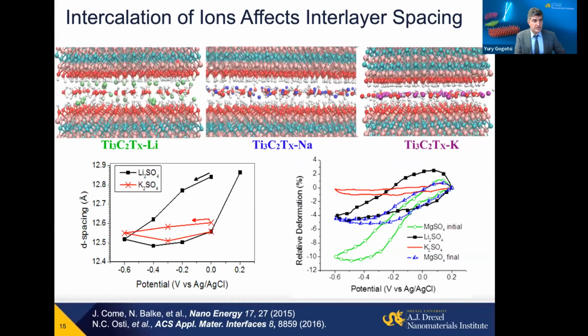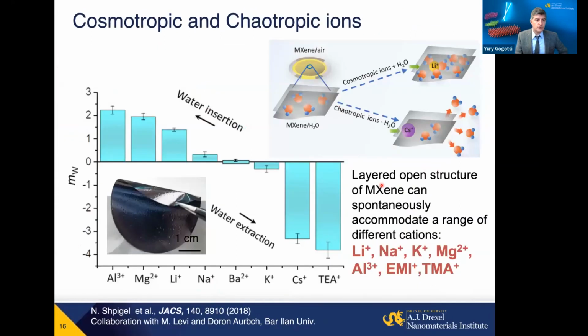For example, if you look at water and solvated ions in water, aqueous ions between layers of MXene, and start bringing more and more ions, some ions will actually lead to electrostatic contraction between two negatively charged layers. When you bring cations, there is electrostatic contraction because of attraction between cation and the surfaces. In some other cases, like potassium sulfate, there will be virtually no change in the spacing, good for, say, battery or supercapacitor energy storage. Large changes, dimensional contraction or expansion, can be useful for electrochemical actuators as an application. So we need to know dimensional changes. Then some ions can bring water in.